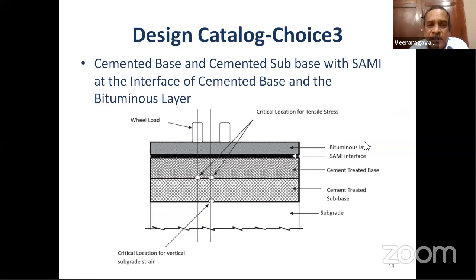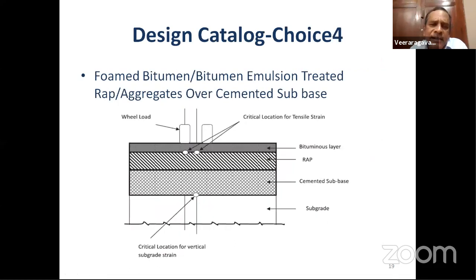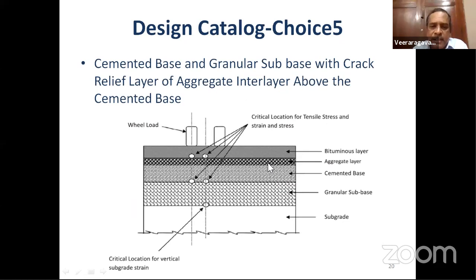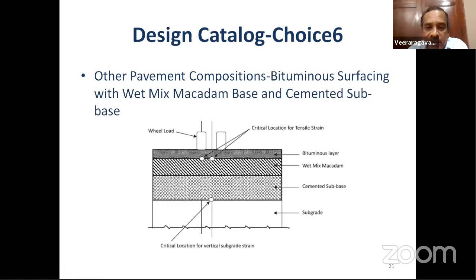IRC came out with a third design wherein, instead of the cement aggregate layer, you can go in for a SAMI, a stress absorbing membrane interlayer, which can be a bitumen impregnated geosynthetic layer, which can retard the appearance of cracks. We also thought that we can reuse the material again and again. Why not use reclaimed asphalt pavement materials? Above the cement treated base, reclaimed asphalt pavement material can be used as a good binder course or base course. We can also go in for a granular subbase, a cemented base, and an aggregate layer. This is another catalog. And lastly, we have a cement treated subbase, wet mix macadam, and a bituminous layer.